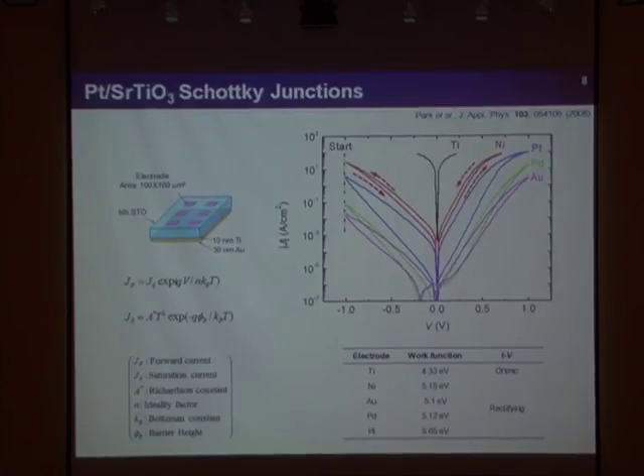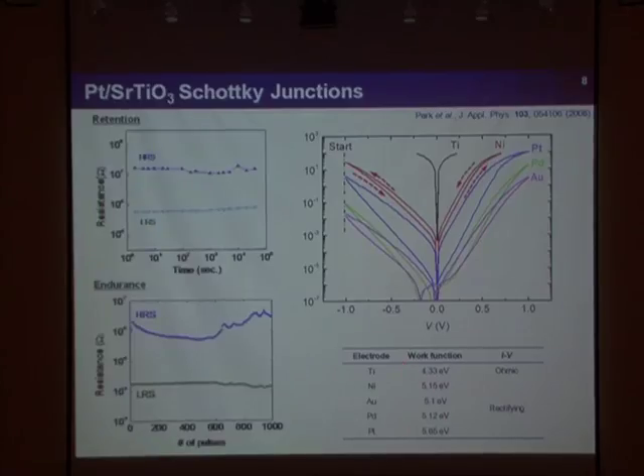So this is one of our first research studies, where we studied platinum/SrTiO3 Schottky junctions. This shows very stable bipolar switching when you use high work function metal electrodes, with good retention and endurance characteristics.